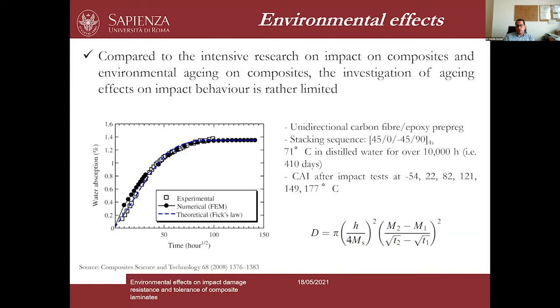These composites were actually subjected to water absorption in water at 71 Celsius degrees for a pretty long time, over 400 days. So here you can see the typical water absorption curve. And we have to mention at first that composites usually follow Fickian behavior under water absorption. And here you can clearly see these results. But one point here we need to mention is that when we have conventional, synthetic composite material, you can see that the level of absorbed water is usually pretty low. So it's around 1.2, 1.4.